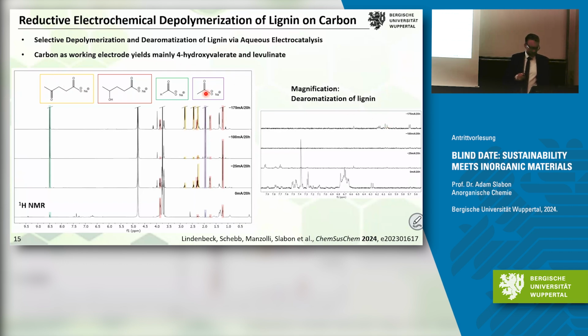So usually when you run the reaction as a control for 20 hours, you see main peaks from levulinic acid and hydroxyvaleric acid. And if you magnify this area here, you see that you have a complete de-aromatization.